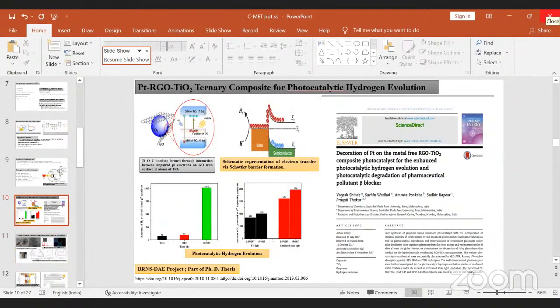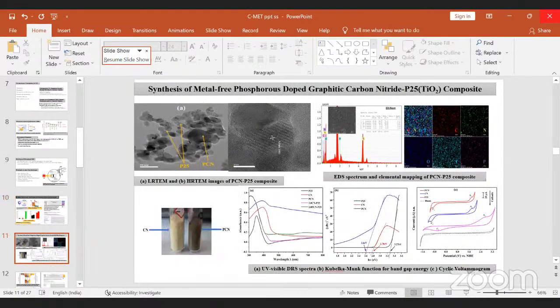But just lowering the percentage of platinum in the system will not be that practical, as we want to go to a metal-free system. Okay, we don't want any metal to be there. So for going to that metal-free system, we thought we can use the graphitic carbon nitride system. It is a non-metallic pi-conjugated polymeric material, and it has a band gap of 2.7 electron volt, and the conduction band is also favorable for the reduction of H+ to H2. So we thought, why not use that graphitic carbon nitride and make a composite of it with TiO2.